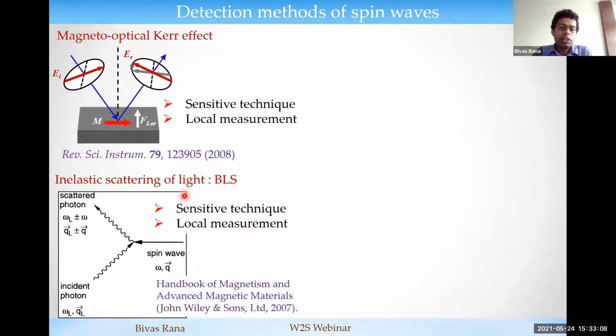And the second way is by using Brillouin light scattering, which is based on the inelastic scattering of light. So basically, if you send CW laser light that interacts with the spin wave, it is inelastically scattered from the propagating spin wave, and due to the scattering, the frequency and the wave vector both are changed. Then you measure how much the frequency and the wave vector are changed by the Brillouin light scattering technique, and that's how you can measure the spin wave properties.